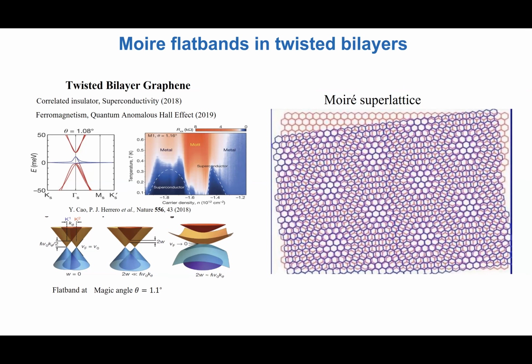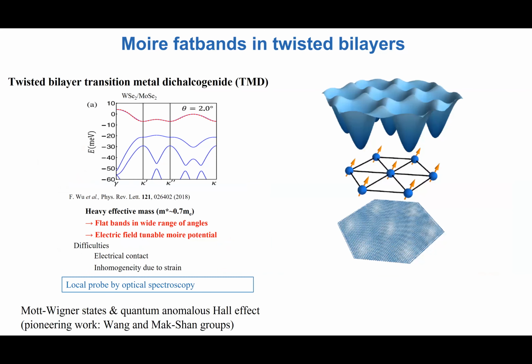But generically, this doesn't happen, as is schematically illustrated here. I mean, here you have a gap between these two due to the tunneling coupling, but you preserve the Dirac cones, and in that case, you will not have isolated bands. Now, this is not the case if you have massive parabolic bands. So when you have parabolic bands, all you do is you introduce a periodicity, which basically defines new bands. Other questions? And everyone can hear me well.